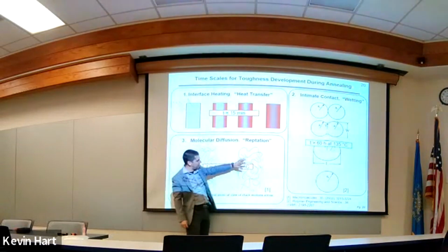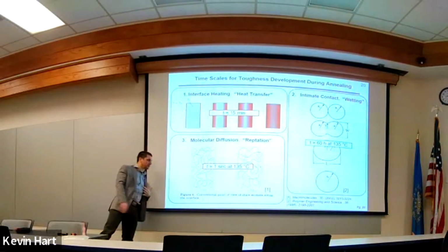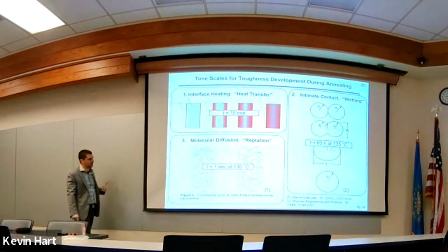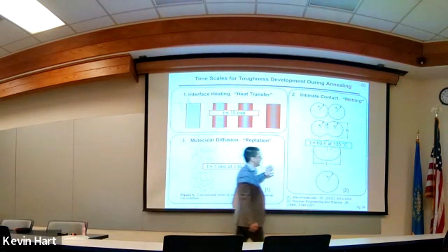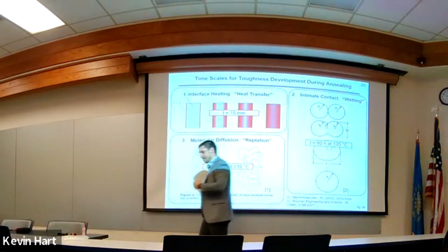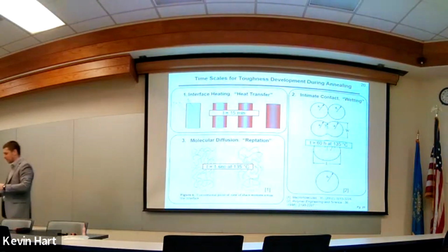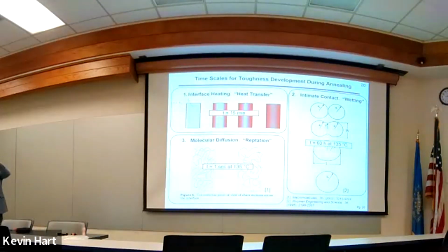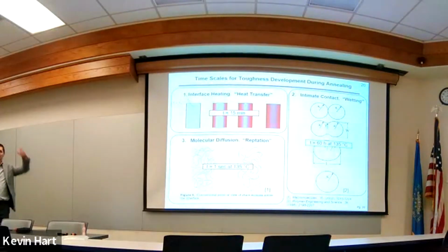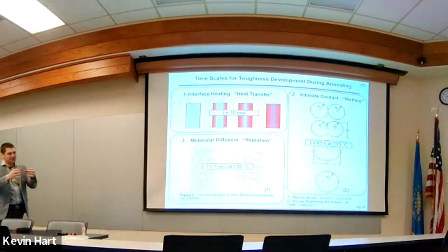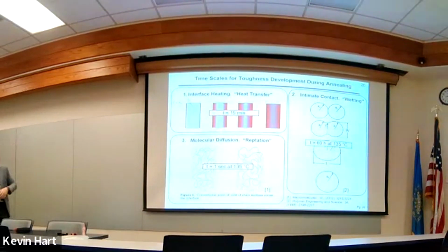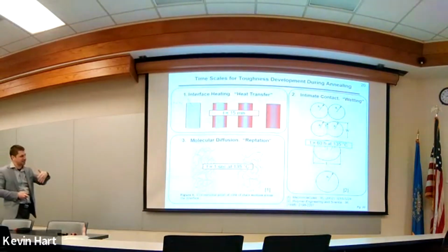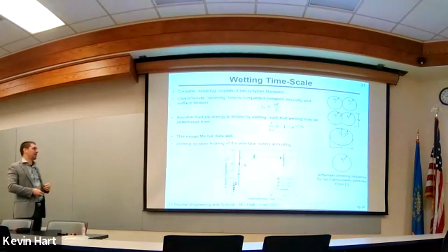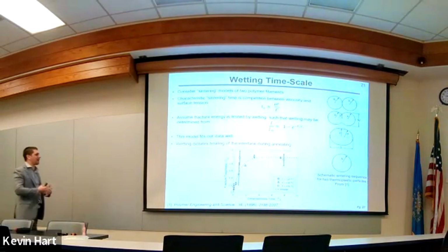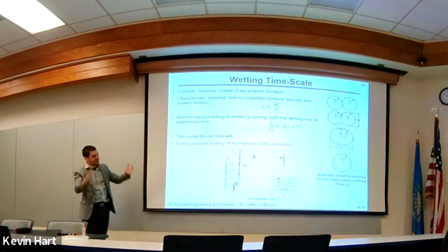This reptation, which is these polymer chains migrating across the interface, turns out that actually occurs really quickly if you're above the glass transition temperature of the polymer. Very, very fast, about 1 second, in comparison. But it's this intimate wetting actually that really takes a long time. These two rods, they have to melt and meld into each other, it's like raindrops on a car window, right? You got the two raindrops hitting each other and then they absorb into each other. All right, it's the same kind of idea here, except you're doing this at a stationary state, right? So there's math associated with these, but this wetting is the rate limiting step. And you can go through the math and make some models and predict about how long it's going to take for this intimate contact, this wetting to occur.